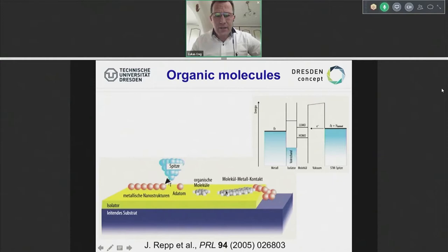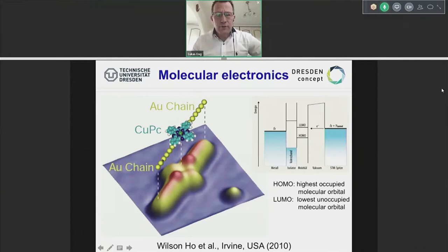Organics, like shown here, is a very popular topic in order to really make nanoelectronics out of this. So what we need is some contacts that are contacting these electrodes. And it was really Wilson Ho, a couple of years back, who showed for the first time that you can really do that, take a chain of single gold atoms attached to this molecule, which is a copper phthalocyanine. You see one, two, three, four-fold, a copper atom in the center, another lead on the other side, and hence really fulfilling the condition of biasing this single molecule through these two wires. So we're talking about single organic molecule electronics. Well, that's a dream. It's not really working yet, I have to say.